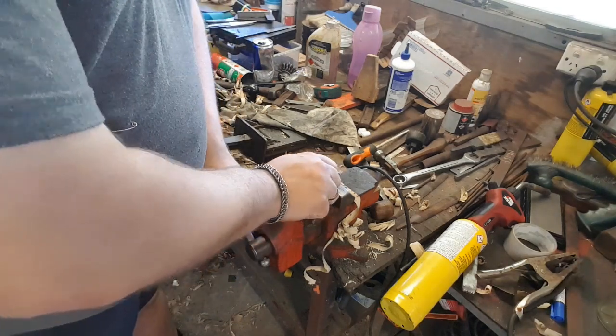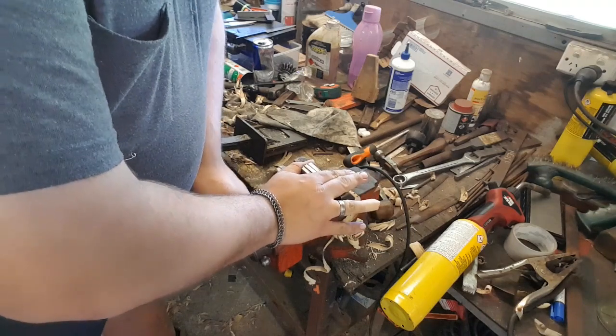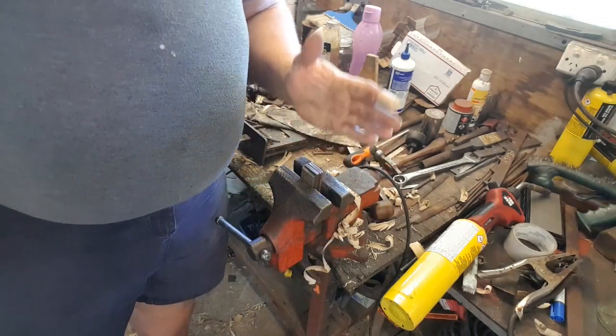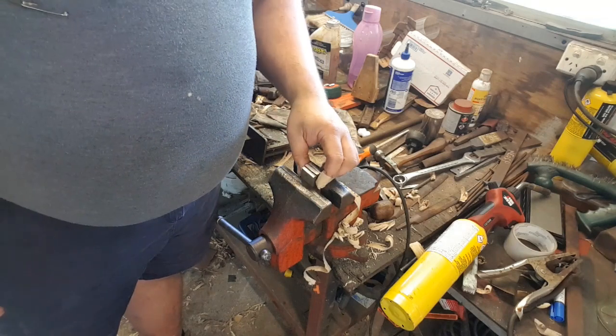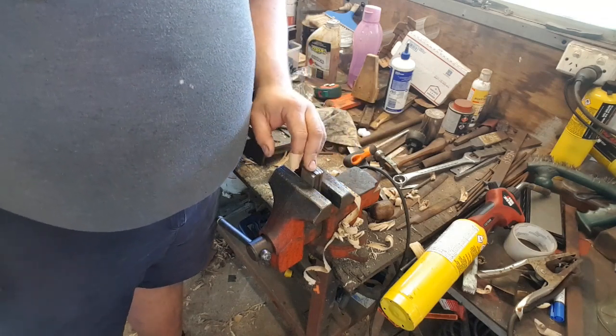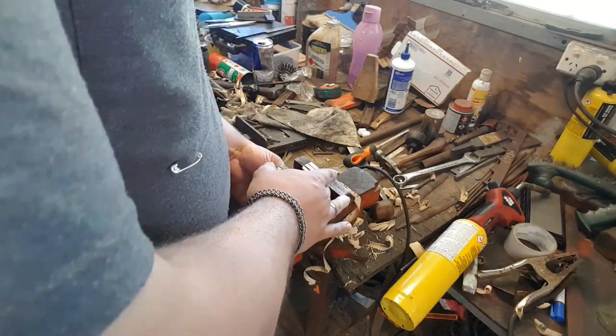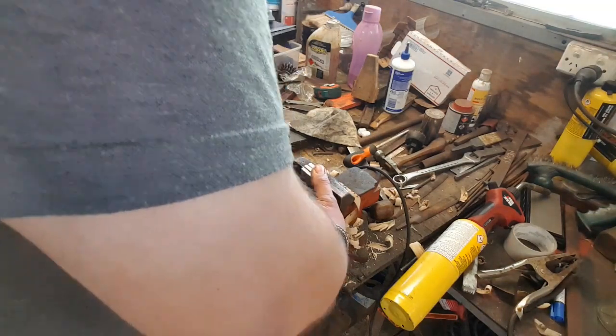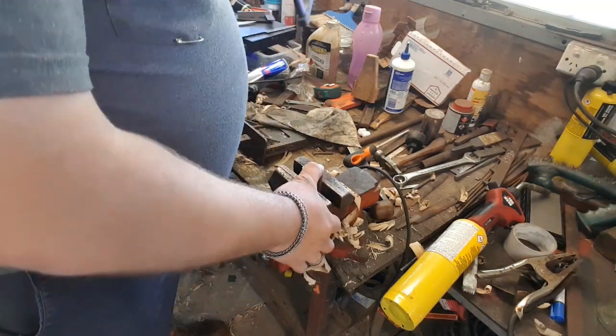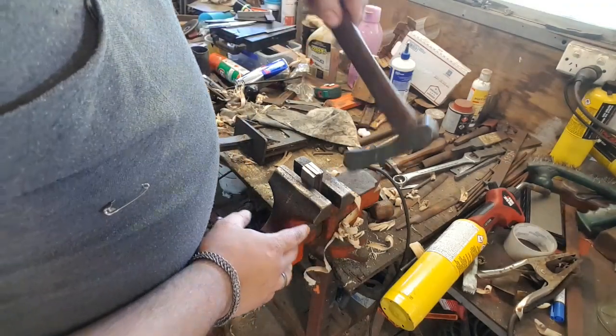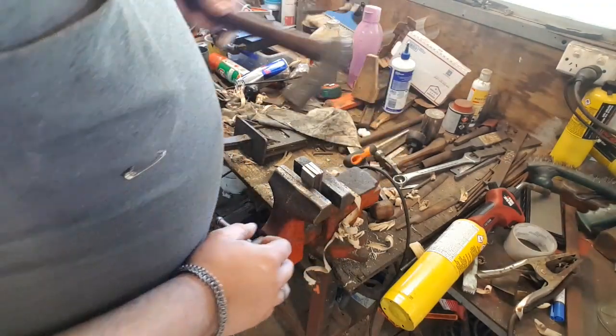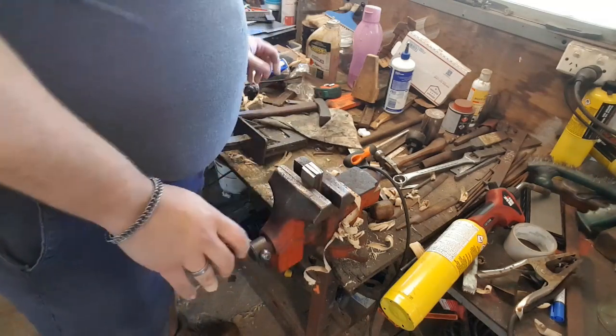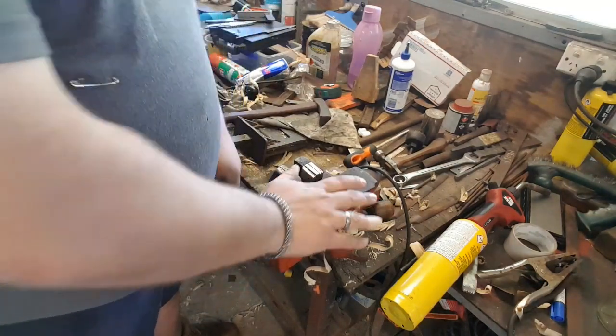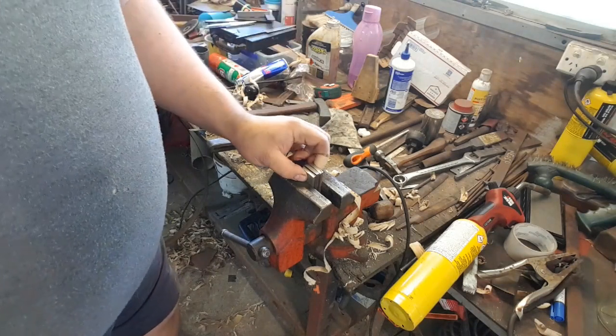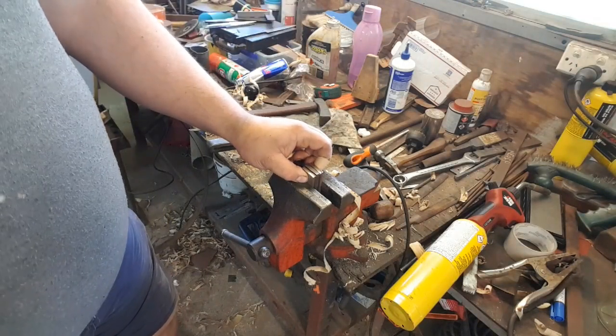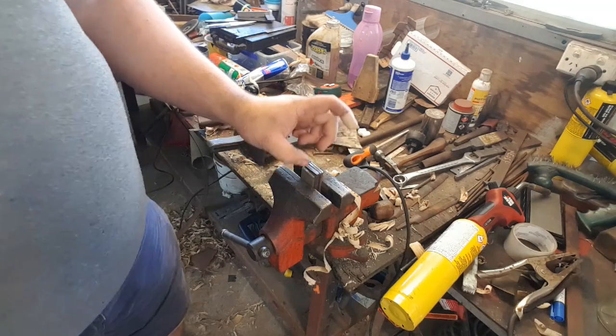If you have a drill vise, those are actually really useful because you can lay the billet on the drill vise base. And that's nice and square, and that means that you'll keep the billet nice and square. In this case, if there's any lack of squareness, all we need is a hammer, and we can just tap it straight as it needs to be, so that all the surfaces are in contact, and then clamp it down nice and hard.